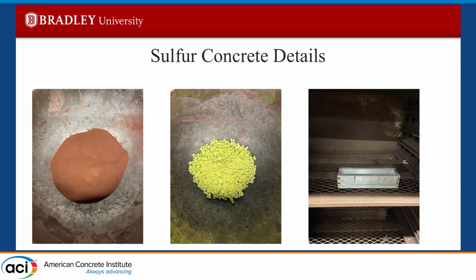Once that's done, you move the mold, and then within 24 hours, you can take it out of the mold. It hardens very quickly, so time is of the essence when you're pouring it. It takes 24 hours to reach 90% of its full structural capacity, which is way quicker than concrete, which is usually 28 days.